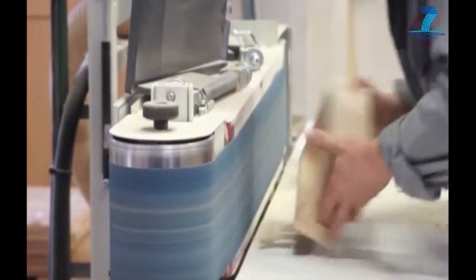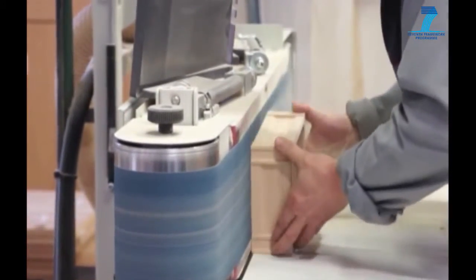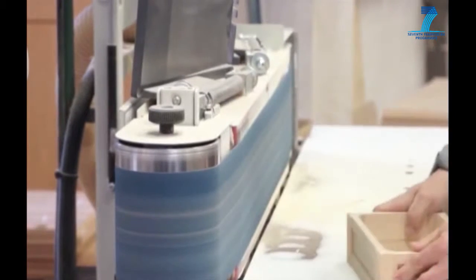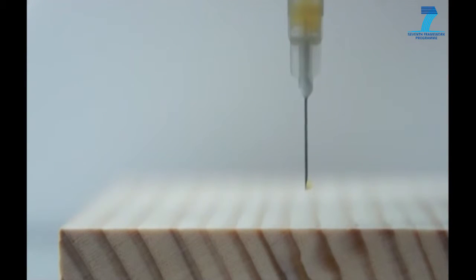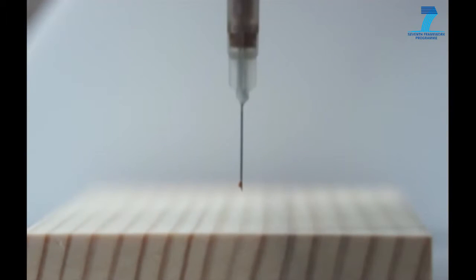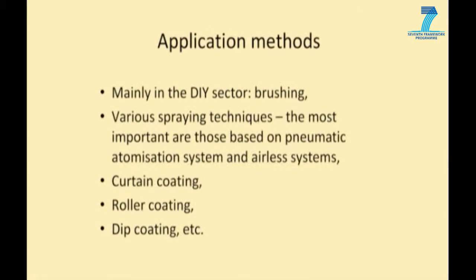Sanding is extremely important because the quality of a wood surface directly influences the wetting of wood by a liquid coating. Sufficient wetting, exhibited by a low contact angle of a liquid coating, is necessary. If wetting is poor, we may later have problems achieving satisfactory adhesion of a dry film to a substrate. Once we have a properly prepared coating system and substrate, we can start with the application of the coating to wood.